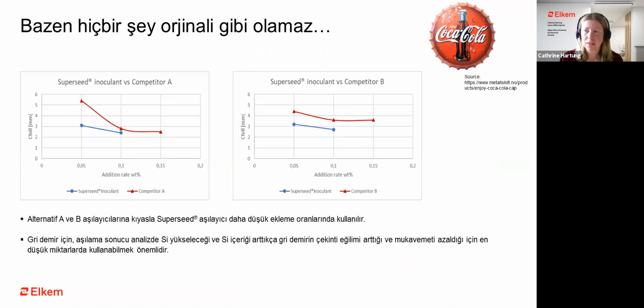Now we go to the next case example. So Superseed inoculant was developed specifically for high strength gray iron back in 1966. So at that time, the inoculants that were used were ferrosilicon or high silicon ferrosilicon, or this SMZ type inoculant. But for all of these inoculants, you had to add quite a lot of them to have the chill reduction. And then by having a larger addition, you also change the chemical composition. So the Superseed brought with it the possibility to add considerably less.